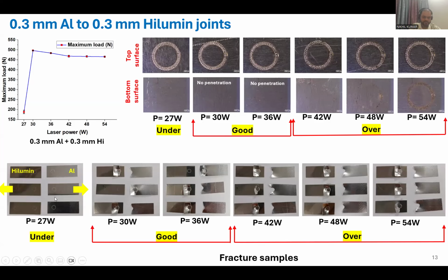So this is not an example of a good weld. According to the definition, the base material should fail; the weld should not fail. Here the weld is failing. That's why you are getting very low strength, less than 200 Newton. Here the bottom sheet is not penetrating. This could be due to very low penetration of the bottom sheet, so you will not have sufficient weld volume.